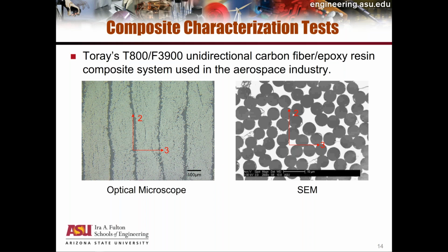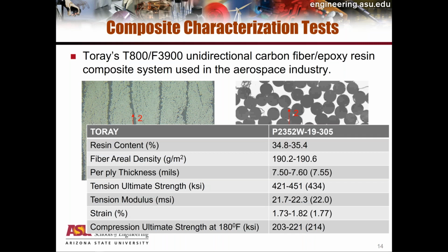So here you see the optical microscope images and the SEM images for this material. Each filament in the carbon fiber is roughly 5 microns. And you can see hundreds, if not thousands of these in each layer. These are the different layers in the laminated composite. These are the resin-rich zones. And you can see here, we make a lot of assumptions when we do the analysis, when we build the model, but in reality, these assumptions are not actually borne out when we examine these materials in high magnified zones and look at it very closely.